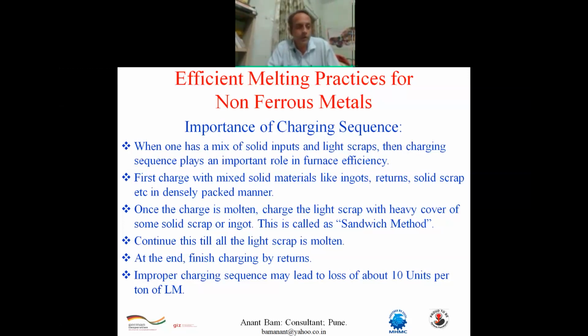The bottom liquid pool will get superheated or it may reach the vapor point of the liquid, but the jammed turning borings above the liquid pool will get jammed at that location and it will never drop into that molten pool. And it may lead to serious melting losses as well as, in remote conditions, it may lead to severe accident cases. So proper charging sequence is utmost important.